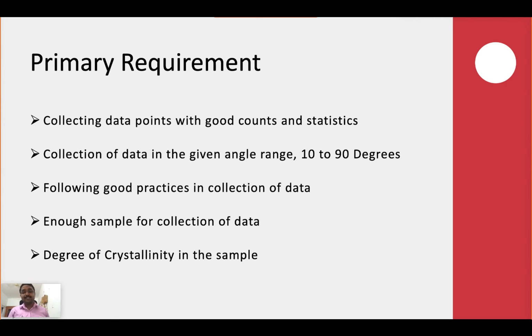And degree of crystallinity is very, very important. If you have a doubt that your sample is having amorphous nature, you should be very careful with analyzing your sample. If the degree of crystallinity is less, you should be very careful in analyzing. So this also is a very important parameter.